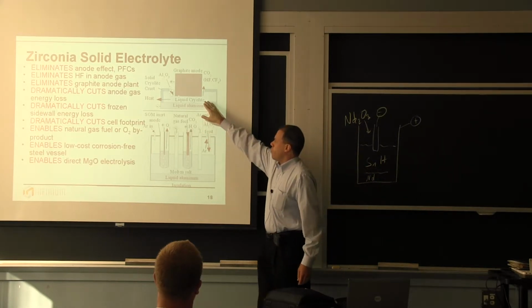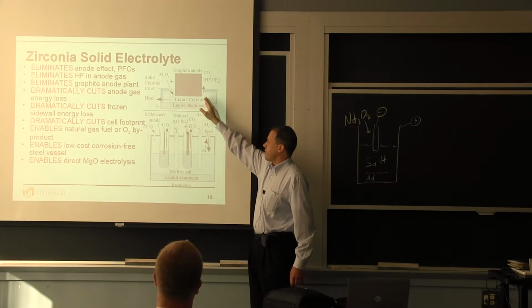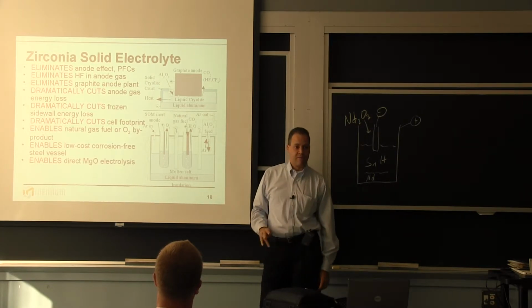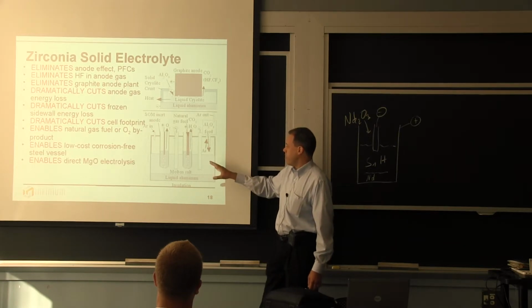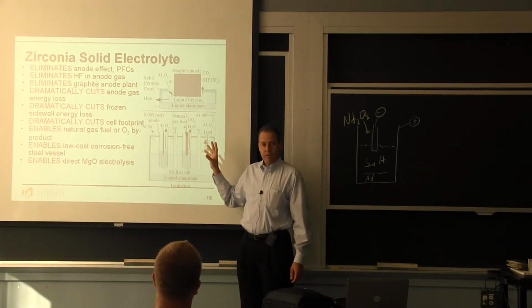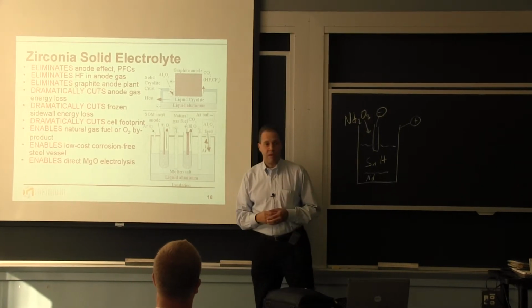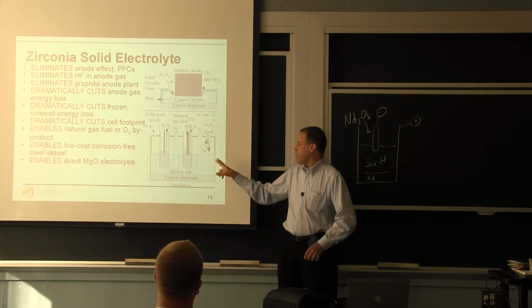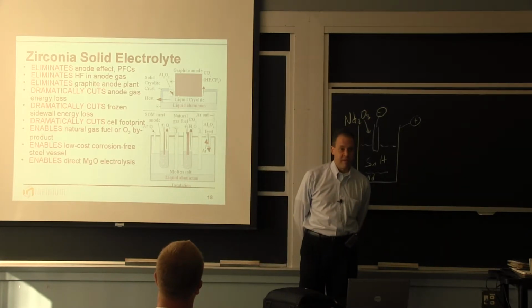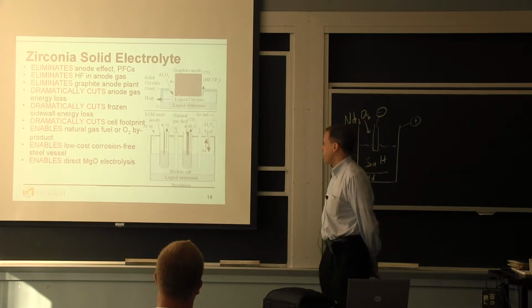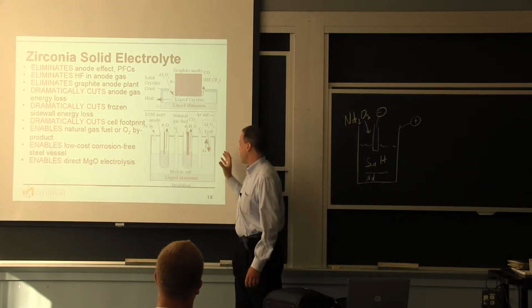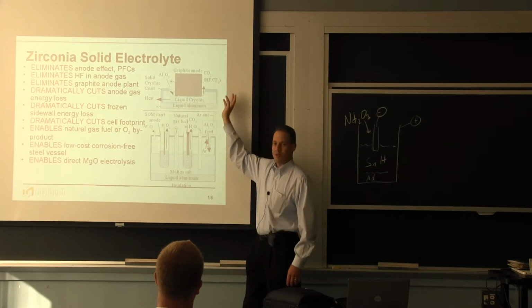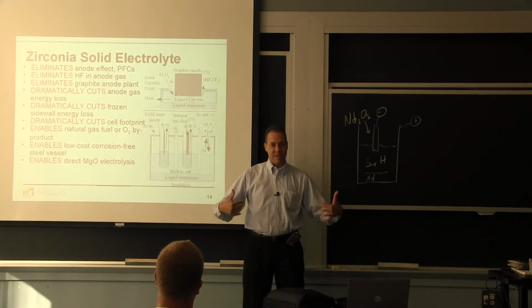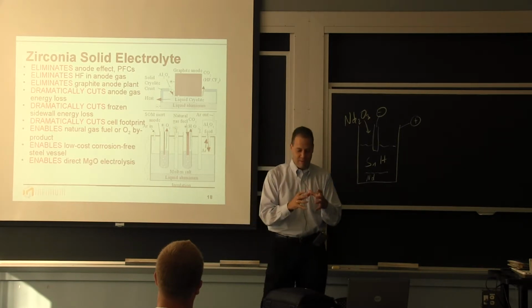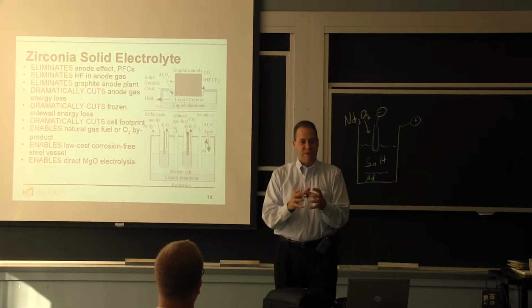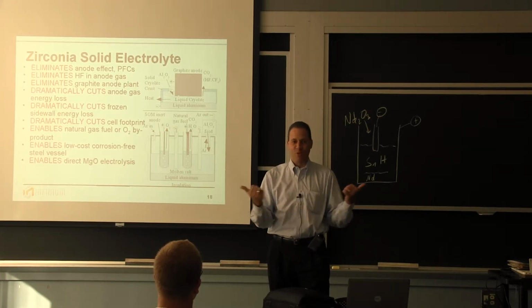Furthermore, the only way to contain this liquid cryolite is in solid cryolite in the traditional Hall cell. In our cell, because you've separated out the anode gas, you have a reducing environment in here, and so there's no CO2, there's no oxygen, and we can contain this in a metal. We can use steel, in fact, just cheap welded steel vessels. And for that reason, we can insulate around it and have very low energy losses. If you contain a liquid in its own solid, it takes a lot of cooling to maintain that solid. Imagine trying to have a long-term glass of water made out of ice, right? If you're heating the water, you have to cool the ice. It's very inefficient.